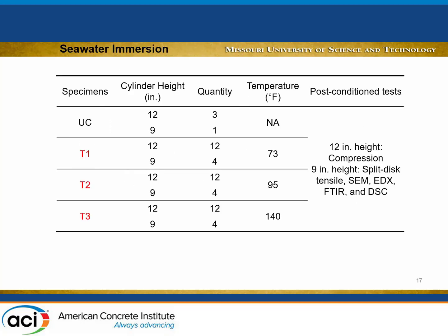The third group of specimens were subjected to, again, unconditioned, and then we have these three different tanks. So T1, T2, T3 representing different temperatures, ranging from, I'm sorry, it's in Fahrenheit, from about 72 up to 140. We ensure that the temperature is constant, so we keep the water moving, and also the salt solution. So we take samples of the water every week to ensure the salt solution concentration is the same.